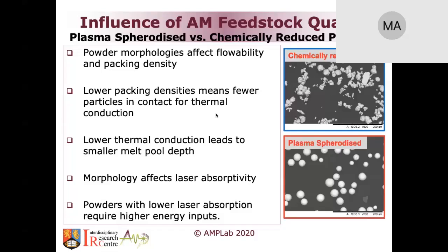In that case, actually, the irregular shaped powder is better, because that will allow multiple reflections of the laser, whereas the plasma spheroidized one will reflect the laser. That's an interesting aspect between spherical and non-spherical particles. And usually powders which have low laser absorption require high energy input, because some back reflection of the laser is going to happen.